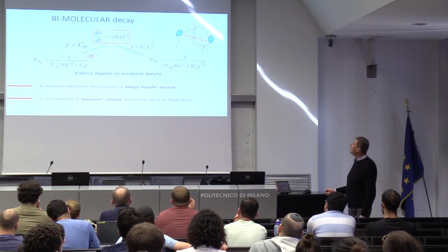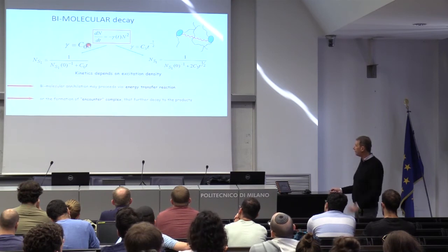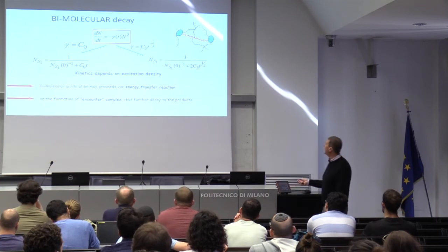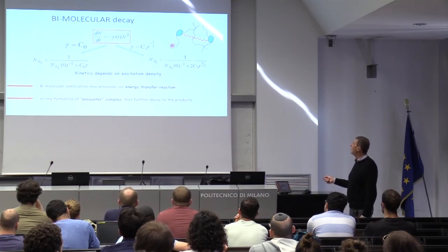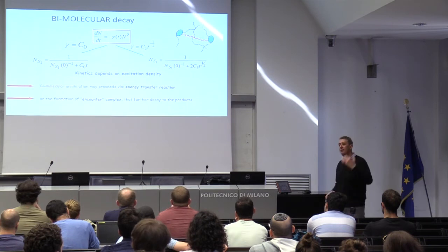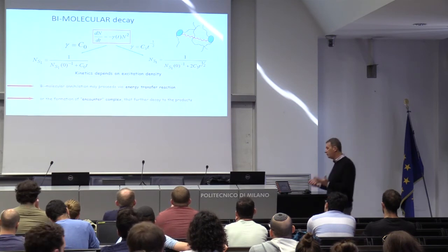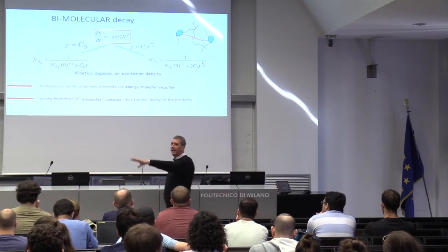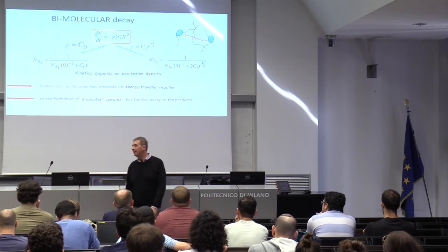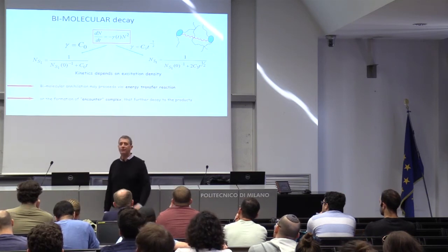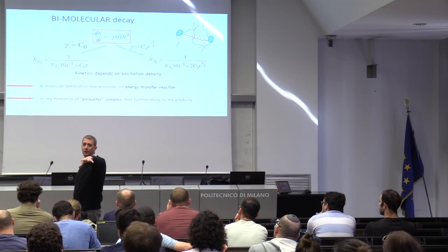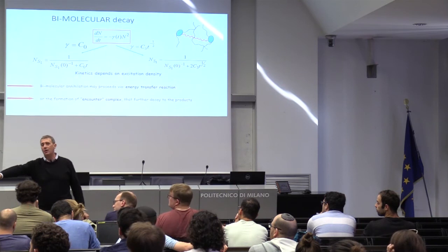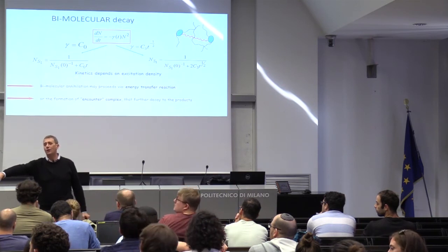You see here again that you can have a constant time. That means that you always have an equilibrium of your system, or you can have a time-dependent decay, which is very common. 1 over square root of time is very common. It means the process is slowing down. That is much more common because it tells you immediately how it is. If you annihilate among each other, well, it's not very nice. So what happens here, for instance, here I have a very dense group, so they will disappear sooner. But here, those are far away, so they will live much longer. So I do not have a constant lifetime.